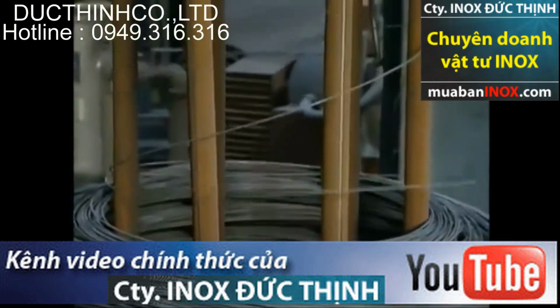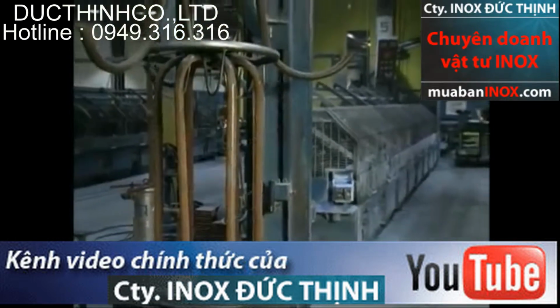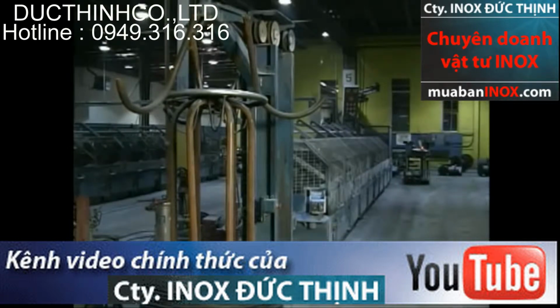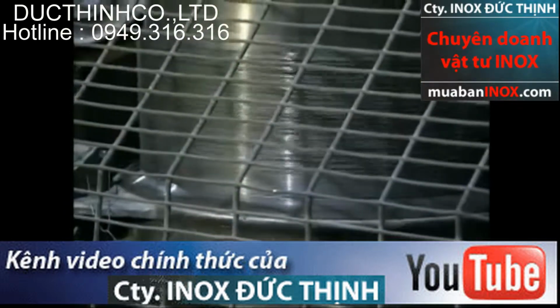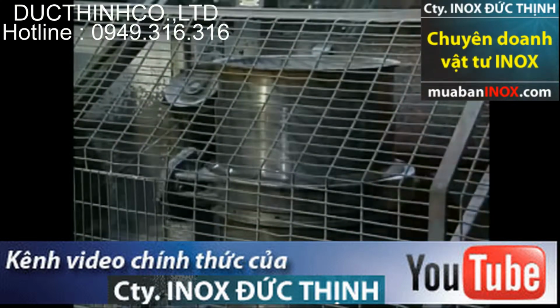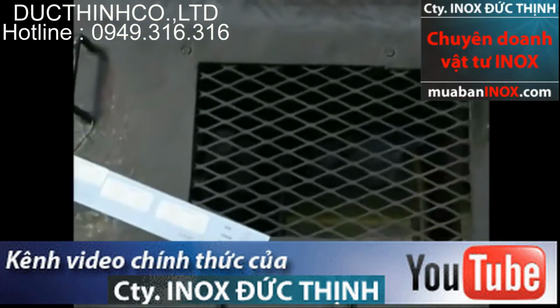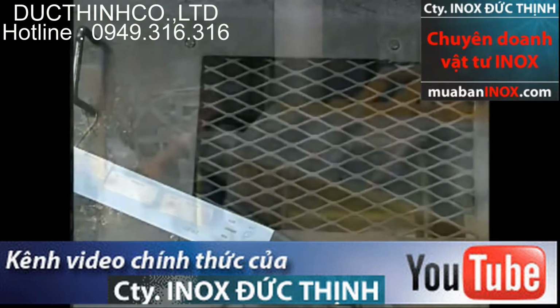In the final wire drawing process, the patented wire would typically begin with a tensile strength of approximately 175,000 psi. Through the cold drawing process, a reduction of up to 90% is achieved through a series of 9 to 13 dies, giving the finished product a tensile strength from 290,000 to 350,000 psi. To comply with identification and traceability requirements, a label will be attached to the bobbin to uniquely identify the product.